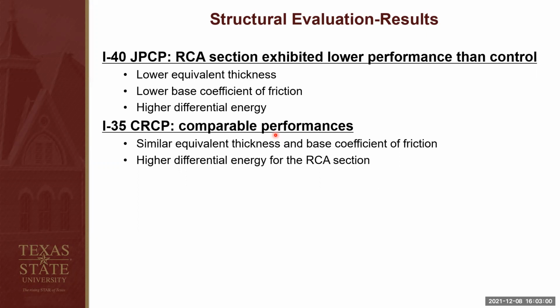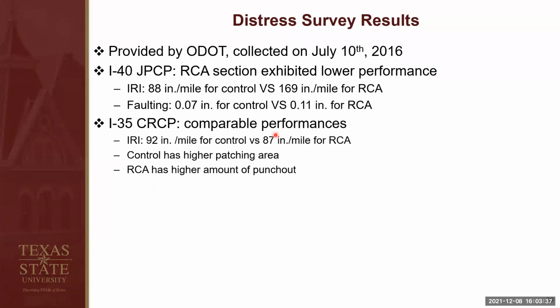The equivalent thickness was lower, the base coefficient of friction was lower, and the differential energy for the RCA was also higher than control. For the CRCP section, however, the performance between the RCA and control sample was comparable. Both the control and the RCA sections had a similar equivalent thickness and base coefficient of friction. But the RCA section still had a higher differential energy, but the performance was really good.